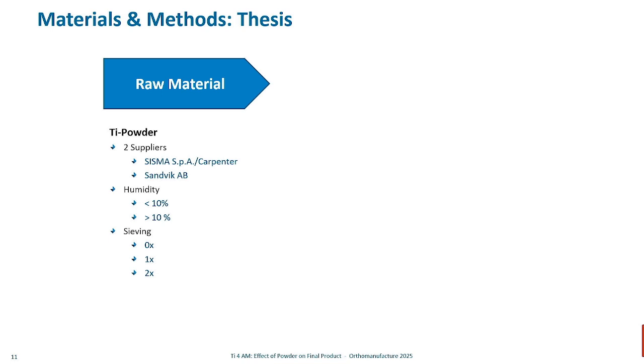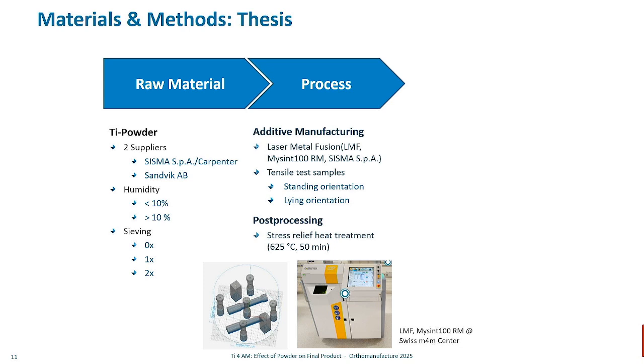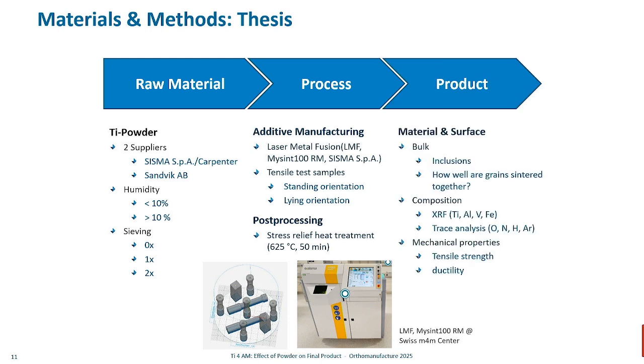So within the thesis, we had two different powder suppliers, SISMA and Sandvik. Humidity was dry, lower than 10%, or higher than 10%, and sieving as a starting material. The process was laser metal fusion in a SISMA device, with different orientations. Some tensile samples were laying, some were in a standing orientation, and there was a post-processing. On the product side, we investigated the bulk, so inclusions, how well the grains were sintered together, then the composition of powder and of the final product, and last but not least, the mechanical properties.